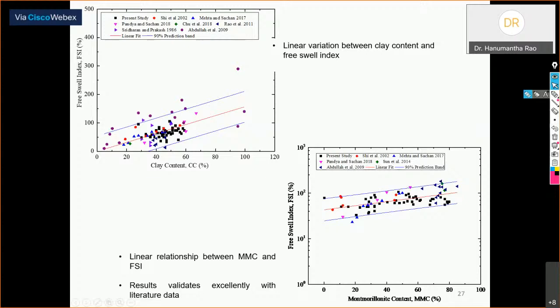that free swell index increases with increase in clay content, as well as the free swell index increases with increase in the montmorillonite content. But if you draw the FSI with the clay content, you can see a lot of variance in the results. But the same thing if you draw with the montmorillonite content, it shows a clear-cut trend. This is because when you talk about the clay content, the montmorillonite may be 100% or maybe other minerals also can exist.